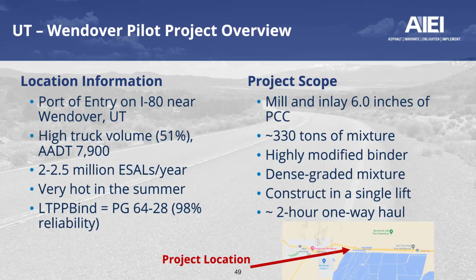And so he actually had $300,000 in the project to mill and remove that material that fall, as he thought that it would not succeed, and to replace it with Portland cement concrete. As we'll see, that caution proved to be unnecessary. This is a dense graded mix, and again, that 6 inches was conducted in a single lift. And it's also noteworthy that this mixture was subject to about a 2-hour haul.